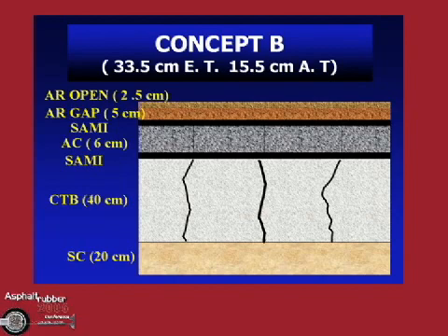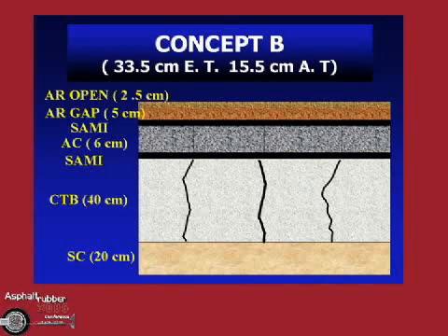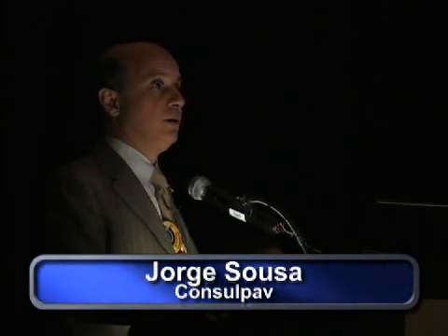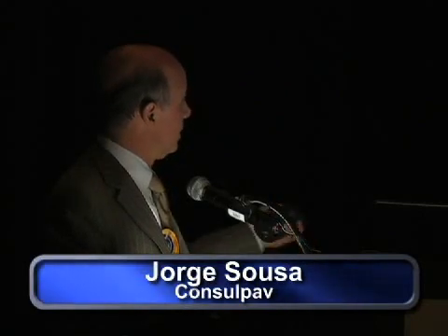So what I'm trying to demonstrate here is that by having these materials, SAMIs, gap grades, open grades, what they are really good at, beyond the fact that they are smooth, they have no splash, they save lives. Why don't we think of them as some new material that can be used to control reflective cracking and design new pavements where there are lots of cracks to be reflected, but we prevent them from reflecting? Therefore, we have fantastic surfaces that, by the way, for Chinese conditions, cost a fraction of the normal pavement structure they use for the high traffic that is considered.